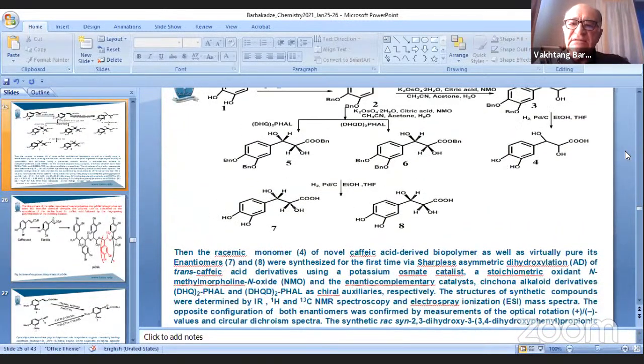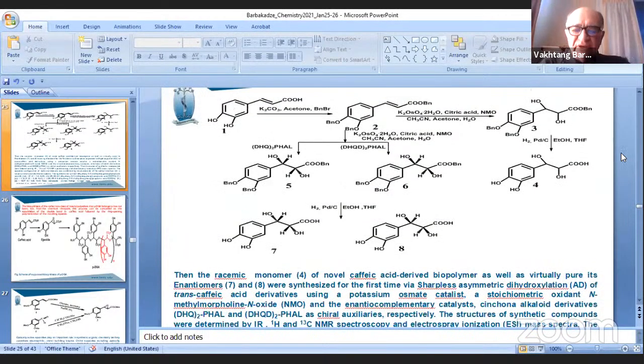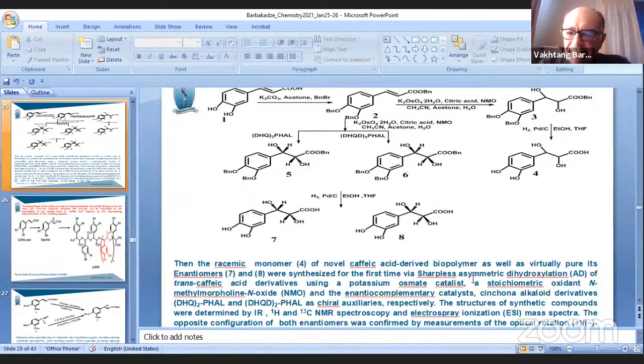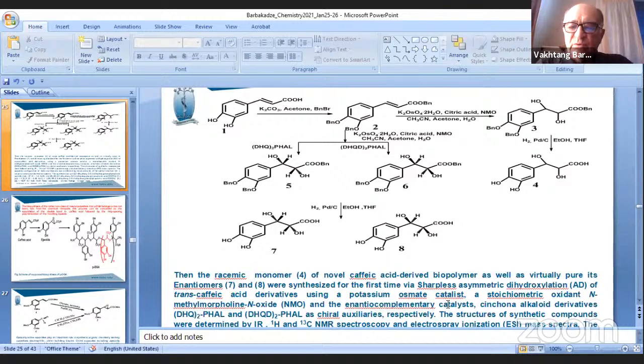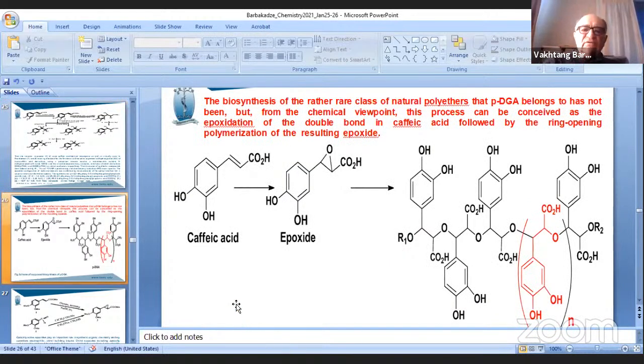Then we synthesized the monomer of this biopolymer using asymmetric dihydroxylation of a trans-caffeic acid derivative using a potassium osmate catalyst. Like this, we got the racemic monomer and two enantiomers of this biopolymer. The biosynthesis of the rather rare class of natural polyethers to which this biopolymer belongs has not been known, but from the chemical viewpoint, this process can be conceived as the epoxidation of the double bond in caffeic acid, followed by the ring opening polymerization of the resulting epoxide.